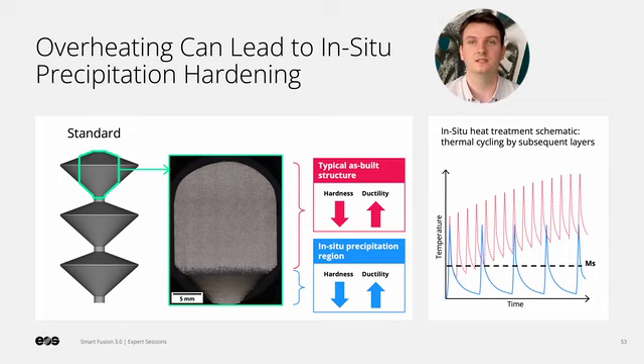The martensite in this region can then be tempered during processing of subsequent layers, and by the heat that accumulates above the thermal bottleneck. If the in situ tempering is severe enough, it is plausible that precipitation can occur. As the diameter of the cone grows, less time is available for cooling, since more time is devoted to the actual exposure. As a result, the initial formation of martensite is no longer possible, and the subsequent in situ tempering is prevented. Now, the question that remains is what happens when we use Smart Fusion to produce the sample.